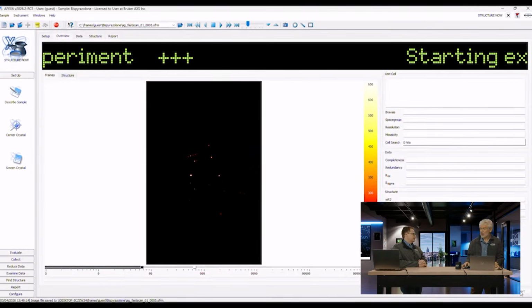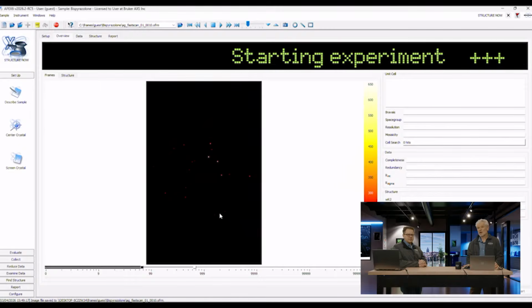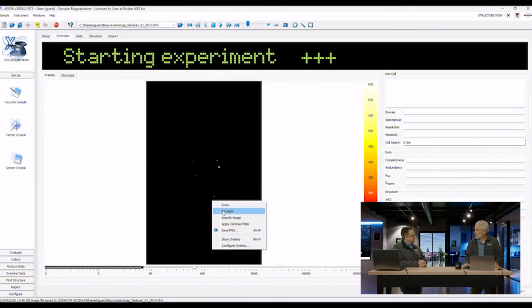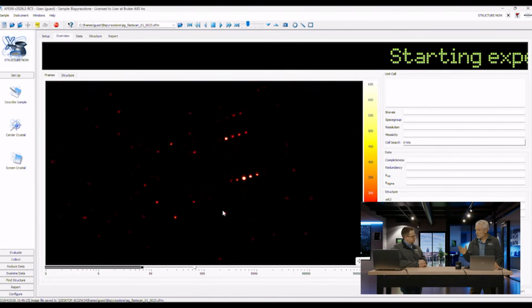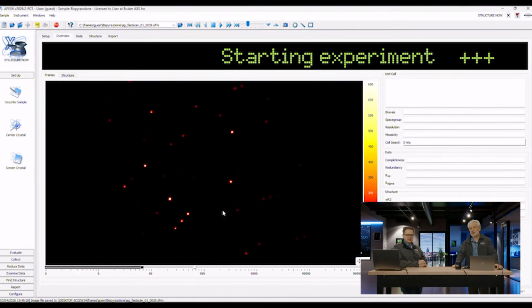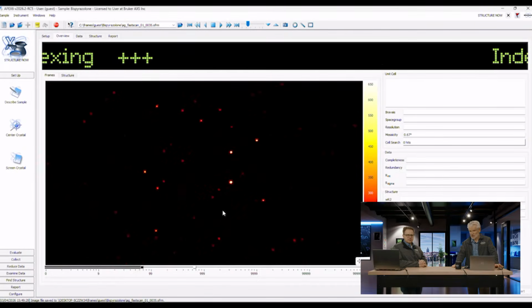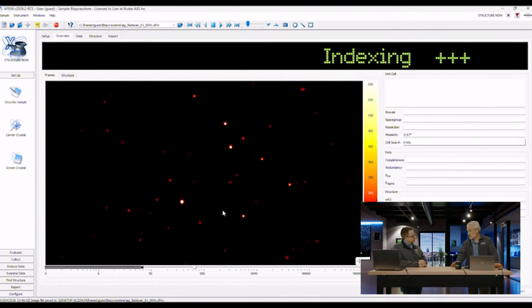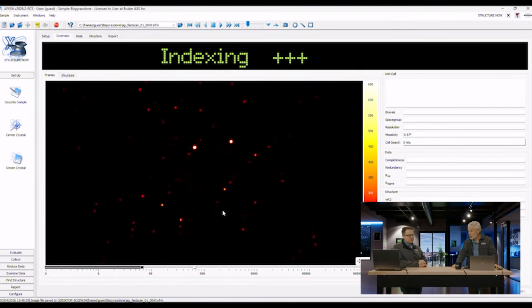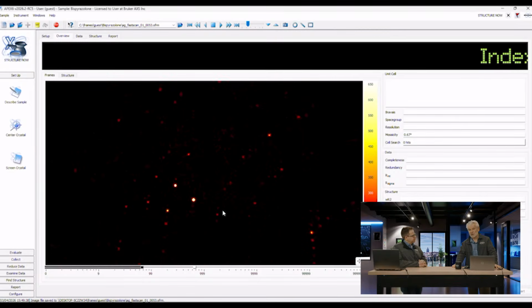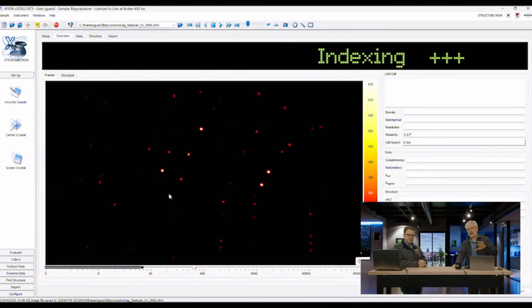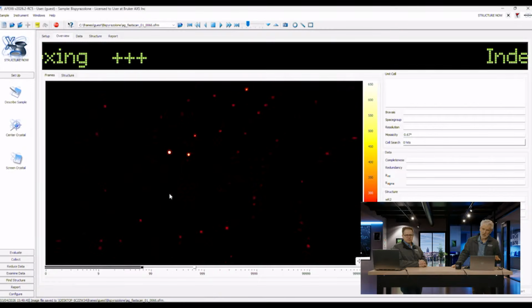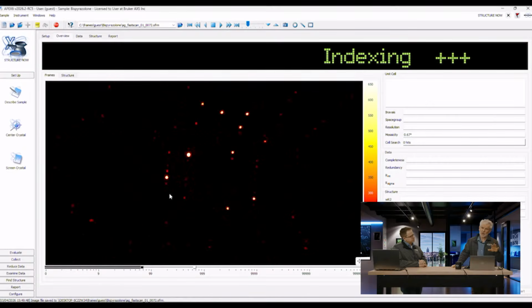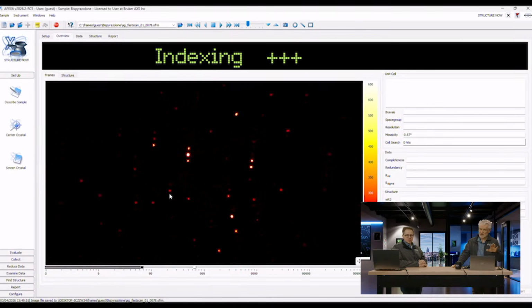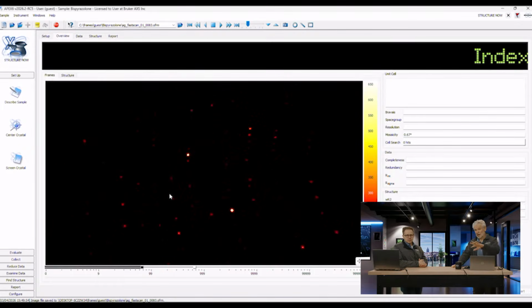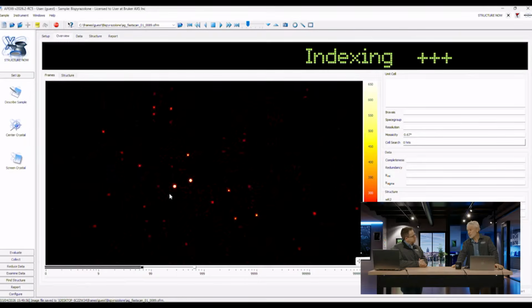This is the structure. I had already filled in the atom types. Click, start, and then it just collects a full sphere of data. You see very short exposure times. I think the default is 0.5 seconds, even with silver radiation, in this case an organic molecule, which might not be considered ideal for silver. I also chose a sample that has a unit cell that's not too small, so we have 20 angstrom unit cell edges. You see the spots are nicely resolved even at a short distance, and at the edge of the detector we get to about 0.7 angstroms.